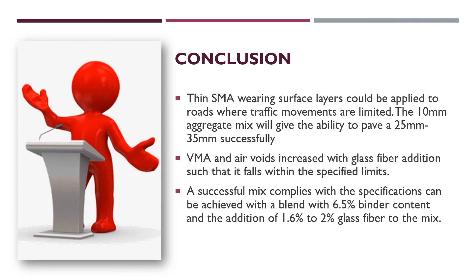Considering all of these results, the following conclusions can be made. Thin SMA wearing surface layers could be applied to roads where traffic movements are limited, and a 10 mm aggregate mix will give the ability to pave 25 mm to 35 mm layers successfully. VMA and air voids increased with glass fiber addition such that they fall within the specified limits in the VicRoads specification. A successful mix complying with the specifications can be achieved with 6.5% binder content and the addition of 1.6% to 2% of glass fiber to the mix.